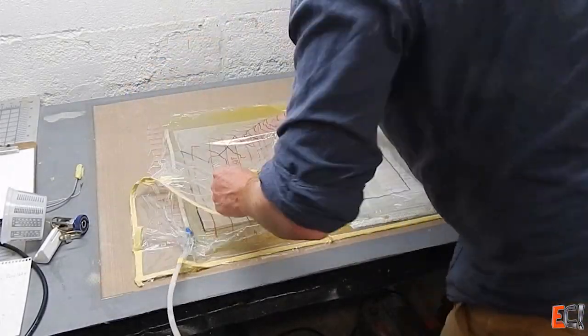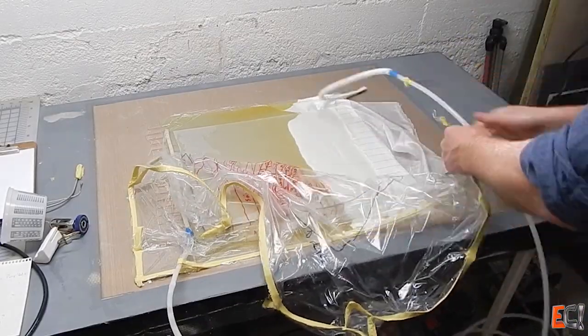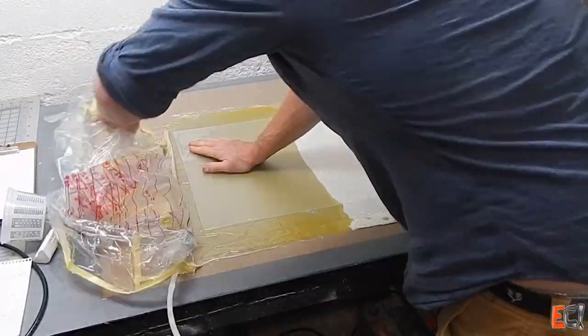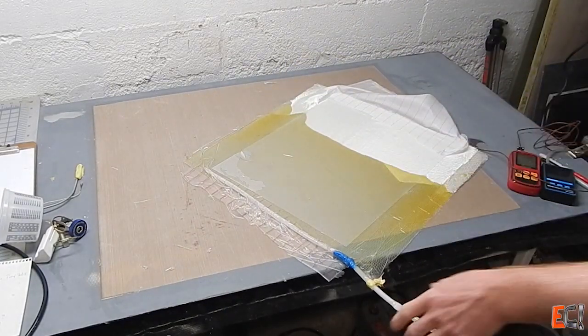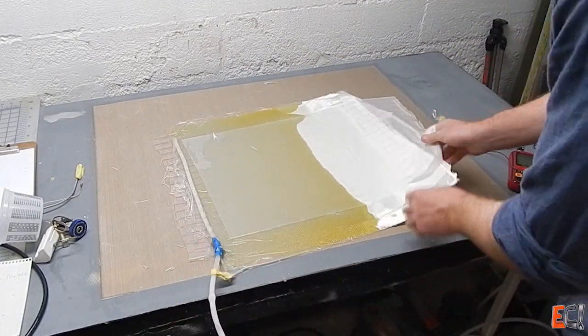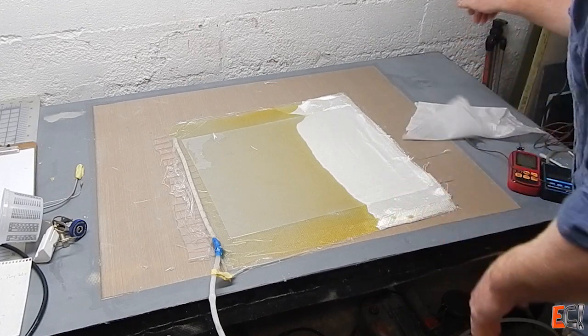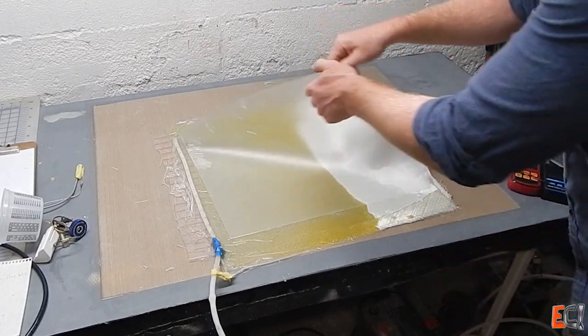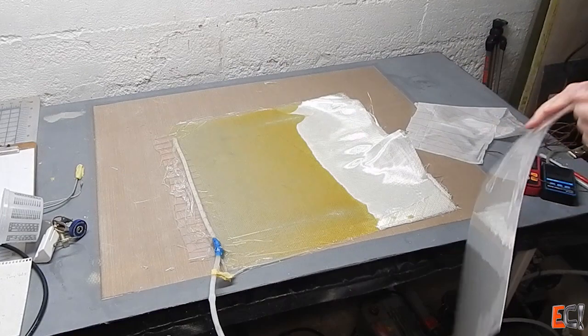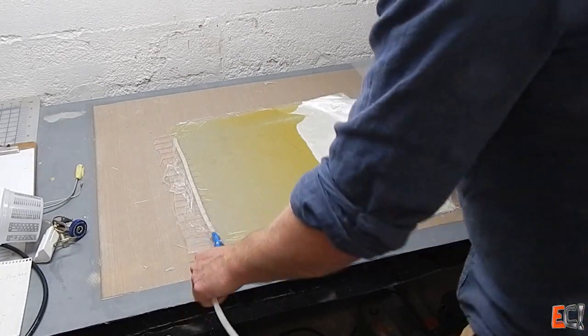So there's the flow. I marked the temperature of both the pot and of the surface. And you can see that resin that had been on the table longest, flowing toward the front, was hot and gelled quickly and turned that yellow color, which I'm assured by the people at ProSet is not a big deal. I've seen it before a lot. It's just when resin gels quickly, it turns yellow, and structurally it should be totally fine. So you can definitely see the gradient there.